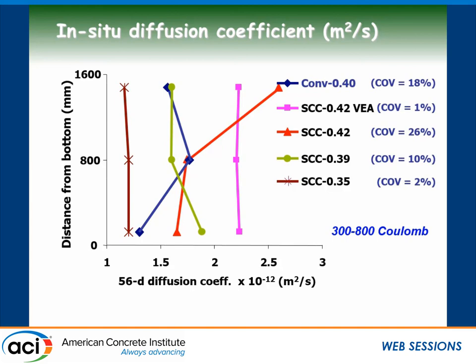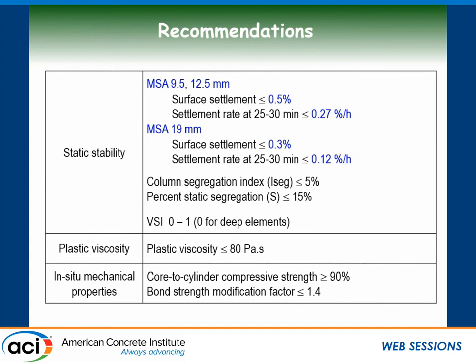So in conclusion, and this conclusion is really about SCC because that's what I'm presenting, static stability is very important for SCC. If you are looking at static stability, you can look at this visual stability index, which is more or less subjective. If you want to do more testing in terms of development of the tests of the mixture or quality control, you can do the column segregation. This is an ASTM test, and there's two different interpretations of the test. But really the one that, in my opinion, gives you the best reflection of the performance of static stability is some indication of surface settlement, regardless of the sample size and how you do it.